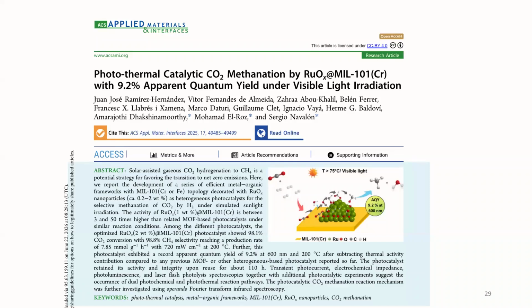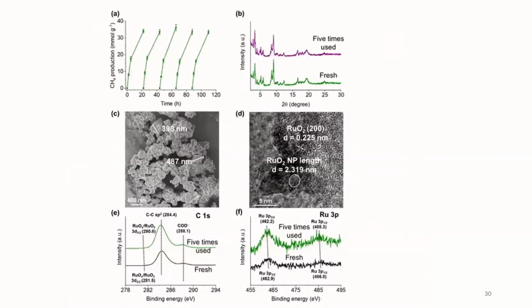And we also checked the stability, so it was reusable. There was no change in the XRD with the fresh and reused solids. These were the TEM images of the fresh and reused material, and you can also see that XPS did not show any changes. So we have demonstrated that the catalyst exhibited very high activity, and it retained its structural integrity with better activity.